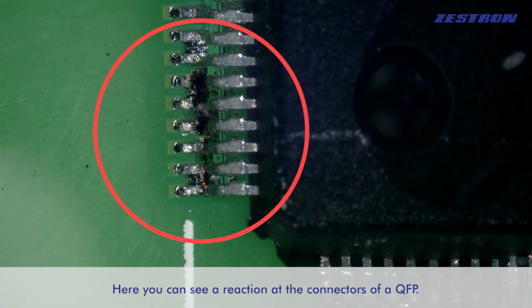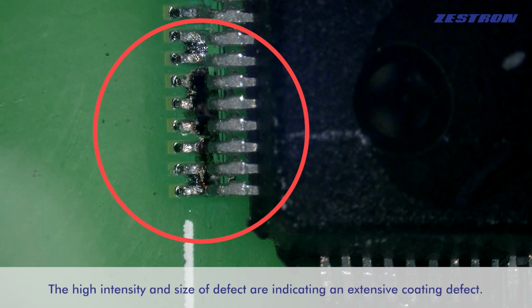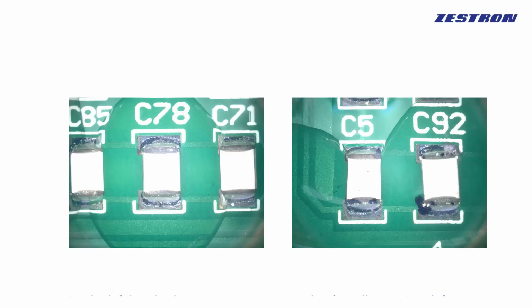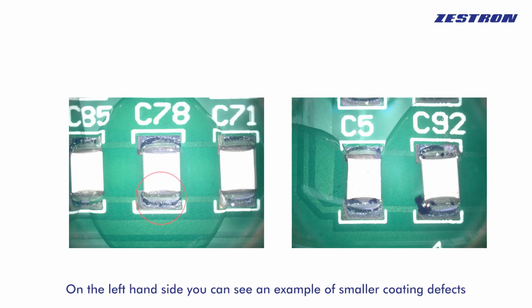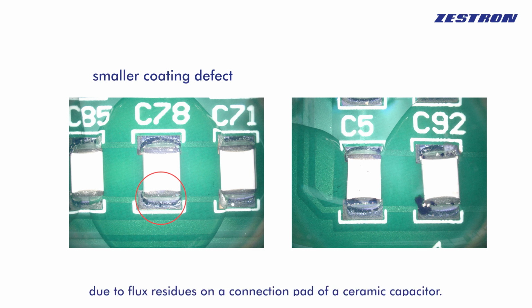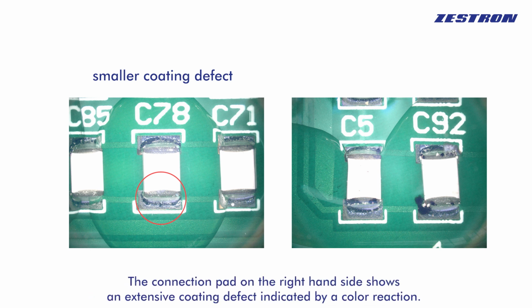Here you can see a reaction at the connectors of a QFP. The high intensity and size of defect are indicating an extensive coating defect. On the left-hand side, you can see an example of smaller coating defects due to flux residues on a connection pad of a ceramic capacitor. The connection pad on the right-hand side shows an extensive coating defect indicated by a color reaction.